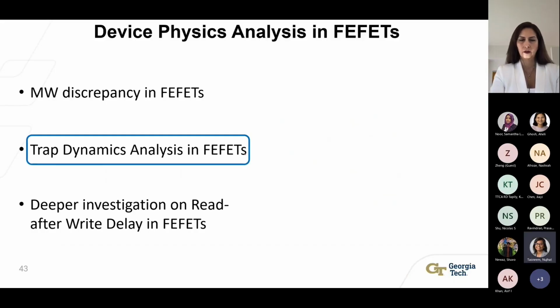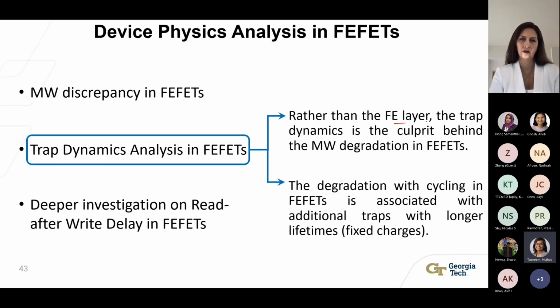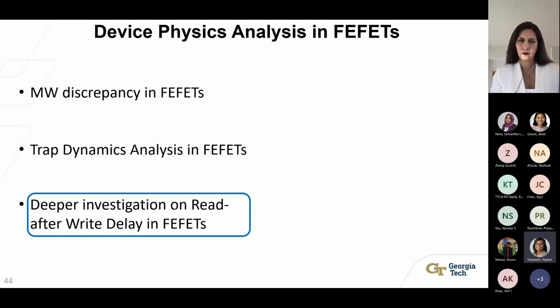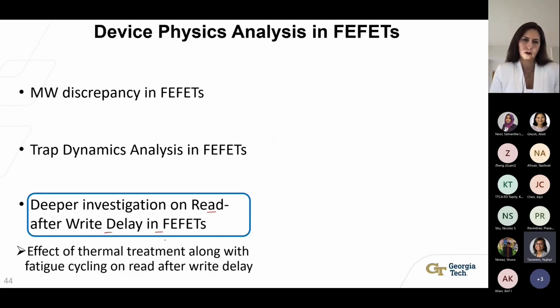So from our work on the trap dynamic analysis in FeFET, we saw that rather than the ferroelectric layer, the trap dynamics is the main culprit behind the memory window degradation in FeFETs. Also, the degradation of FeFETs with cycling is possibly associated with additional traps with longer lifetime or fixed charges. So in our next experiment, we try to do a deeper investigation on the origin of read after write delay in FeFETs. For this, we try to observe the effect of thermal treatment along with fatigue cycling on read after write delay.